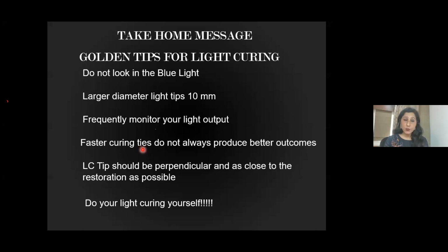Frequently monitor your light output. Faster curing lights do not always produce better outcomes. Remember this fact. Light cure tips should be perpendicular and as close to the restoration as possible. And the best tip is do your light curing yourself, because when you give your assistants the light curing, sometimes they keep it obliquely and sometimes they keep it somewhere else, where the intensity should reach, it does not reach. So do not let your assistants do that, do it yourself.